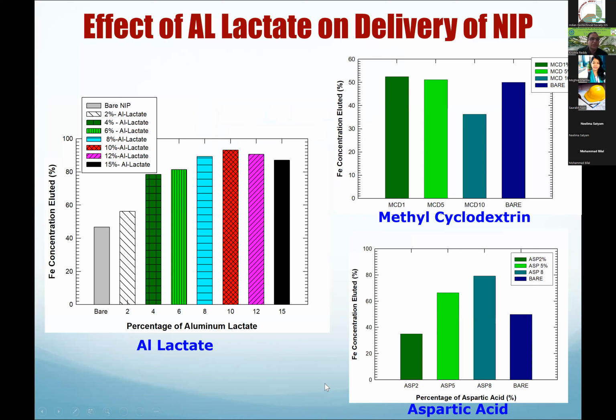So we did those experiments, and from the iron concentration in the effluent, you can calculate how much we put on the top and how much came out into the effluent, as a percentage of aluminum lactate. When you use the bare nanoscale iron particles, you get something eventually, as you keep flushing it. But when you use this aluminum lactate, you can see a lot more coming out from the bottom. That means more nanoparticles are coming out. Again, if you use the synthetic groundwater, even the bare iron could be transported somewhat, compared to deionized water. So this is for the lactates. This is for aluminum lactate, which we found better.